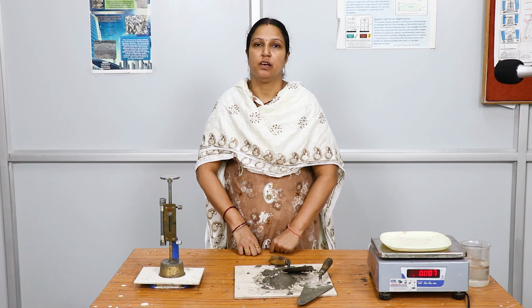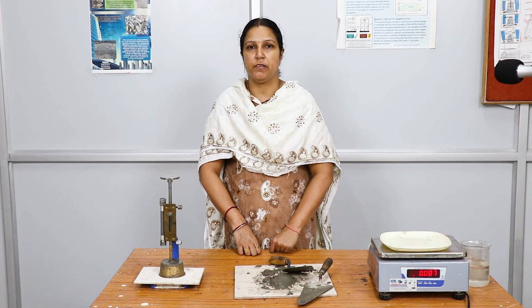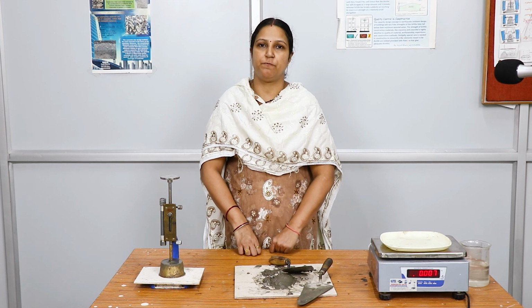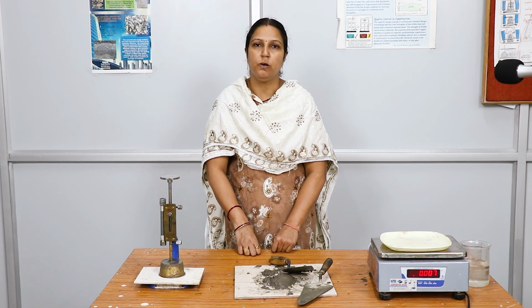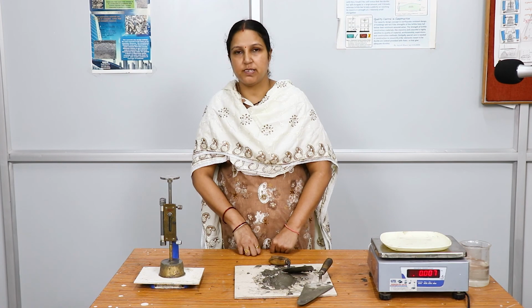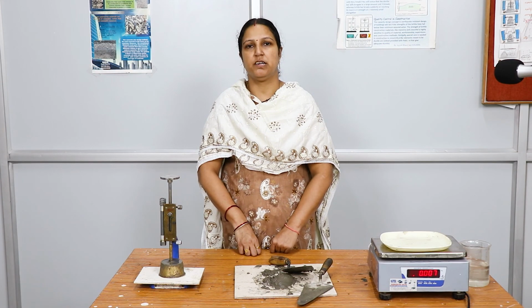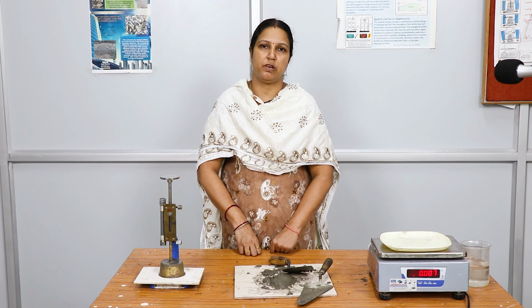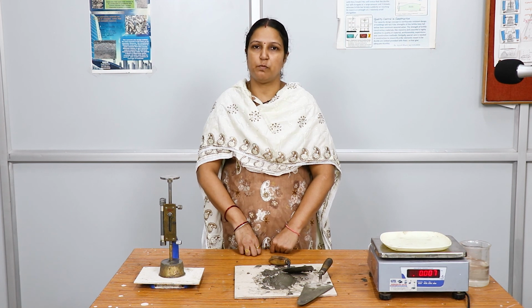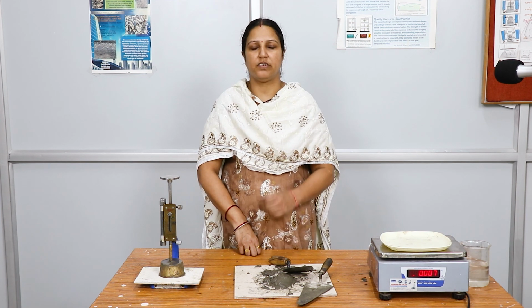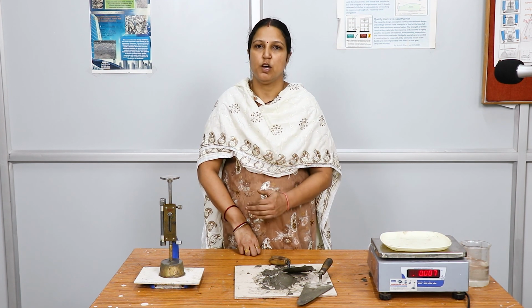As per IS 4031, the standard consistency is obtained when the Vicat plunger penetrates 5 to 7 mm from the bottom of the Vicat mold. So for this cement sample, we obtained a standard consistency of 31%. Varying with the cement sample, the standard consistency also varies, but generally it comes around 30%.